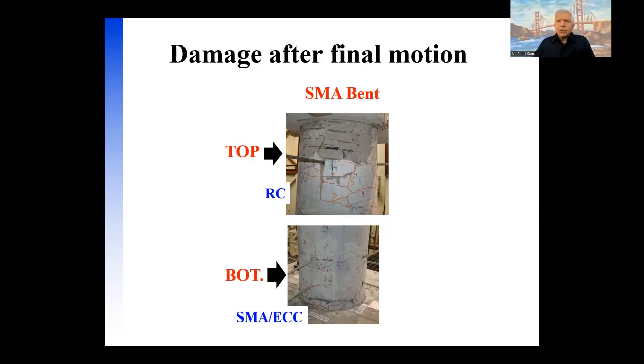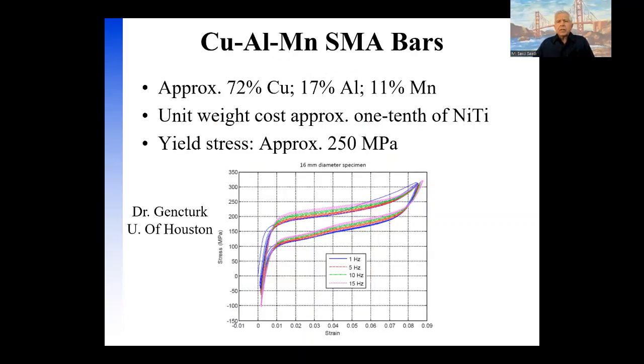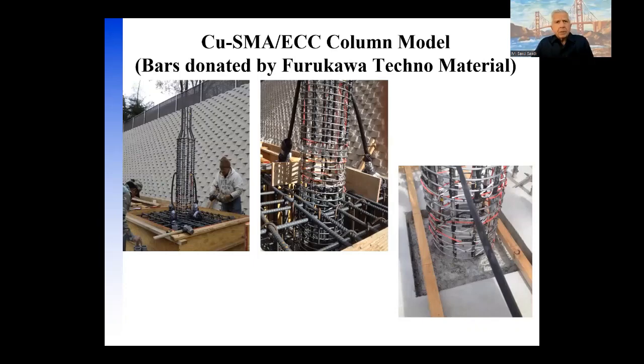Having been convinced that ECC could work well in controlling the seismic damage, and considering the relatively high cost of the first type of shape memory alloy that we had used, nickel titanium, we decided to look at alternative shape memory alloys. This one made with copper, aluminum, and manganese is a lot less expensive than nickel titanium, has lower strength. And there were some preliminary tests that showed that, yes, there is good potential for this material. So we decided to adopt that in one of our projects and use the copper shape memory alloy in combination with ECC again, and built a large-scale column model, and tested on a shake table.